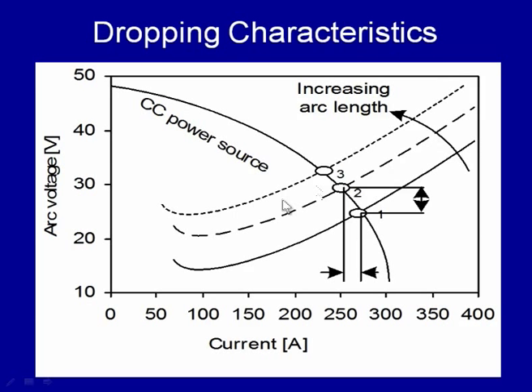If, due to any reason, the arc length is increased, we will have different welding conditions. With the increase of arc length, the arc characteristic is shifted to the higher side. The second line indicates the arc characteristic with the higher arc length. The intersection of the arc characteristic with the higher arc length and the characteristic of the power source leads to another operating point, that is operating point 2. In simple words, if we increase the arc length, there will be a change in operating point from 1 to 2.